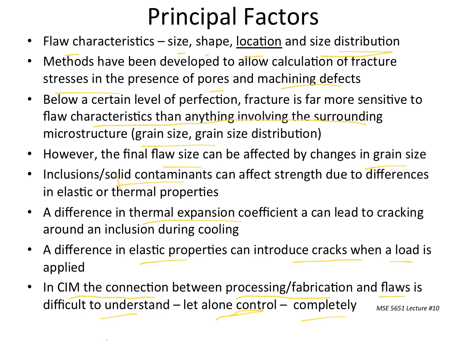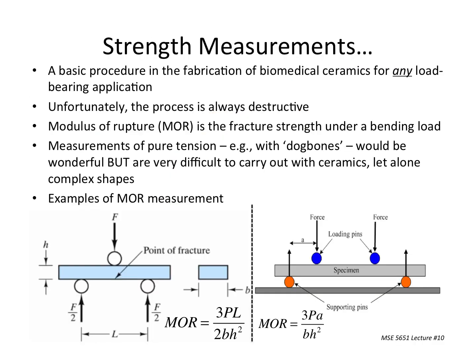All right, it's not like a nice liquid. And so what we do is we estimate. Process is always destructive. We do modulus of rupture. This is a 3-point bend test. Over here is a 4-point bend test, which is definitely better. We can't really do what is done in metallurgy and make dog bones out of ceramic. Just can't do it. It's too hard. All right, but what we can do is make flat surfaces and stress them with 4-point bends and 3-point bends and generate these modulus of rupture loads or mechanical strengths for these systems.